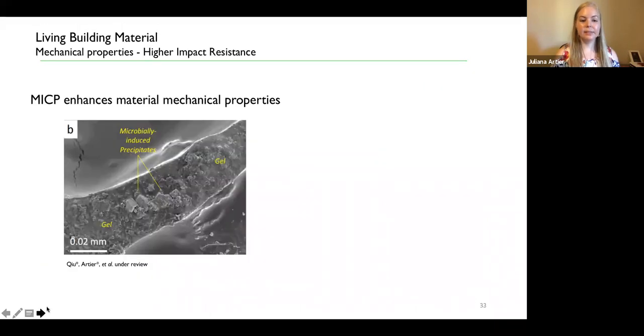So as we were all talking, you can see here in this SEM of the LBM being produced, that the area between the gel and the sand has clearly precipitated calcium carbonates. And we know that the calcium carbonates can bind to the sand, but I just wanted to make sure to show you that this is clearly being seen.